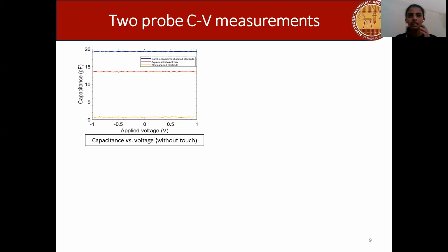We know that nanoparticles will show a better conductivity compared to the silver metal, and hence they'll show a higher capacitance. And secondly, we have used photopaper instead of PET, because of which we can observe very slight, but some kind of change in the capacitance. If we see here, the block-shaped structure capacitance was observed to be significantly low compared to the square spiral one, while in the simulation case, they were observed to be comparable, which means the difference between the capacitance obtained in case of block-shaped structure in simulation and the experiment are more comparable compared to the other 2 structures.